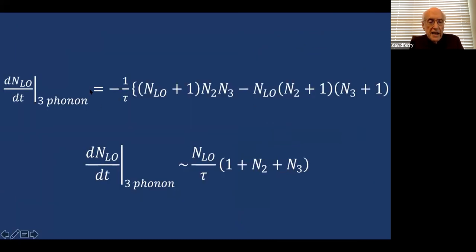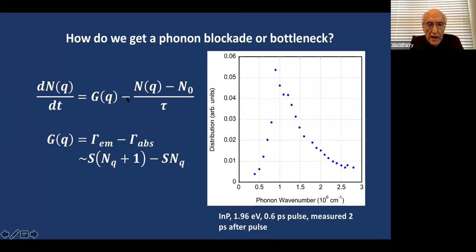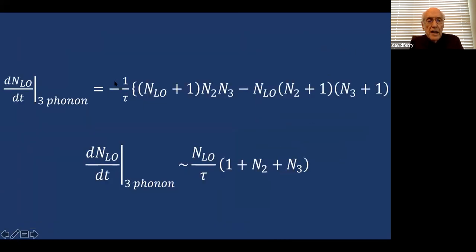Let's come back to that decay constant. Let me go back to this term right here, and let's write it more effectively. So here's the 1 over tau. This is the emission process, emission by the LO into an absorption by the 2 other phonons. And the reverse process is absorption of the LO and emission by the 2 other phonons. And you work all this out, you discover it's kind of like the LO mode population times 1 plus the other 2 populations. Now these can have different energies in the different processes. In the Klemens, they have the same energy, and so they have the same temperature dependence. In the Ridley, they have different energies and they're going to have different temperature dependencies.